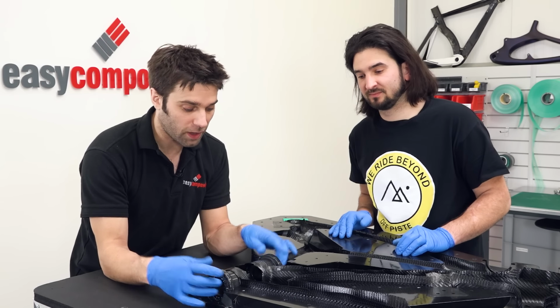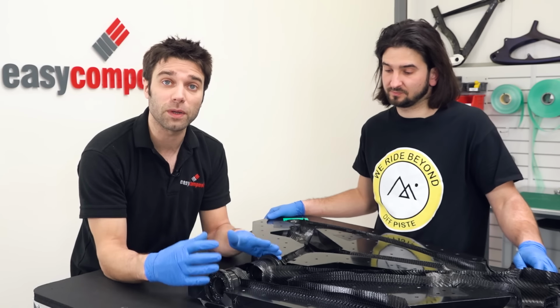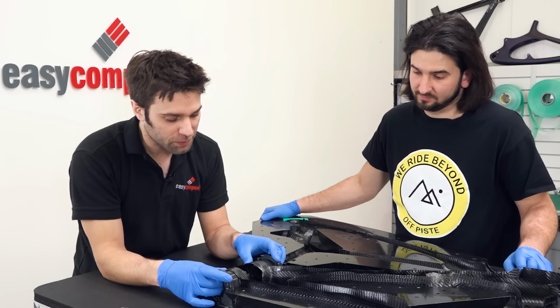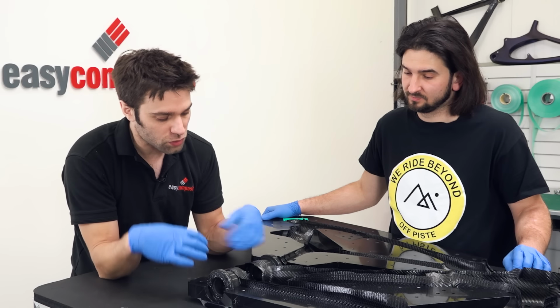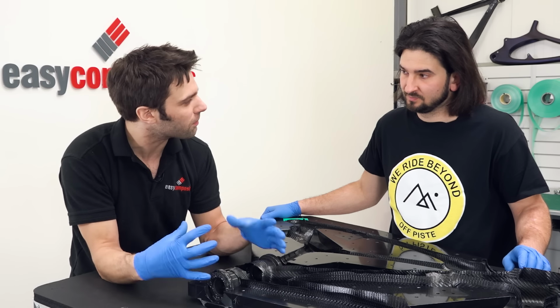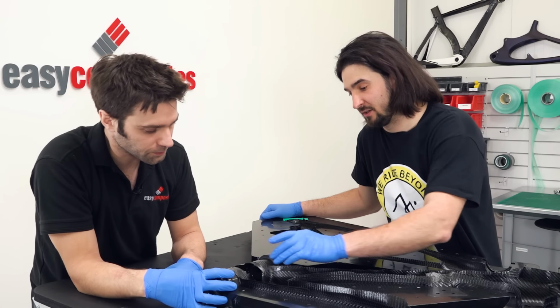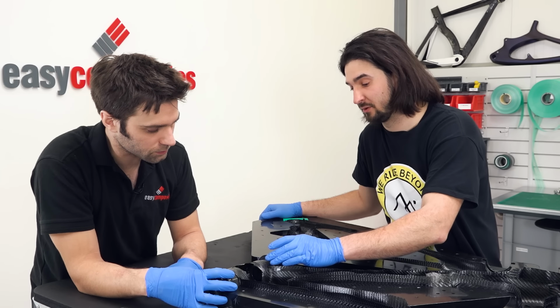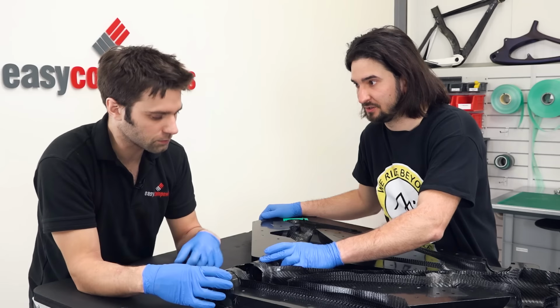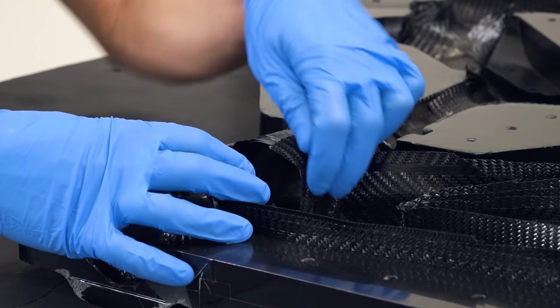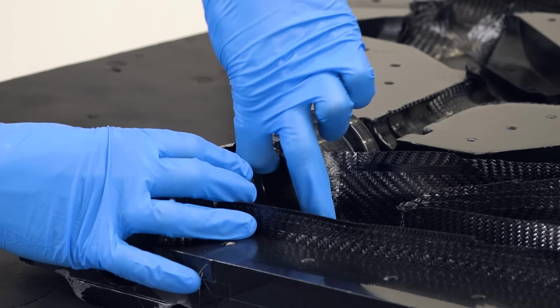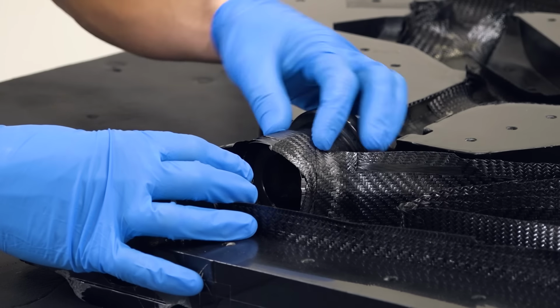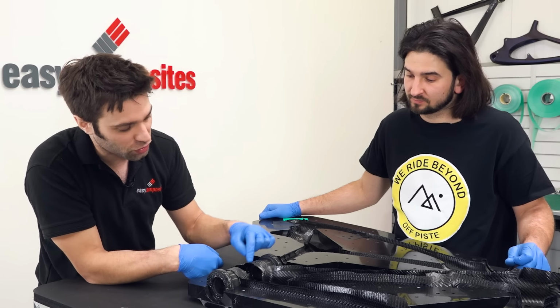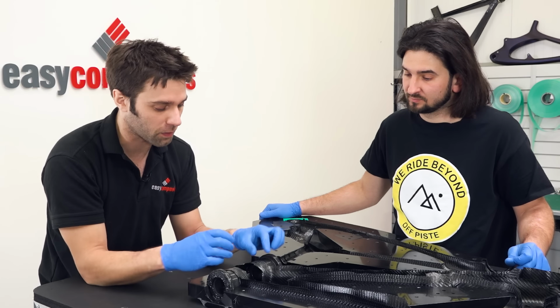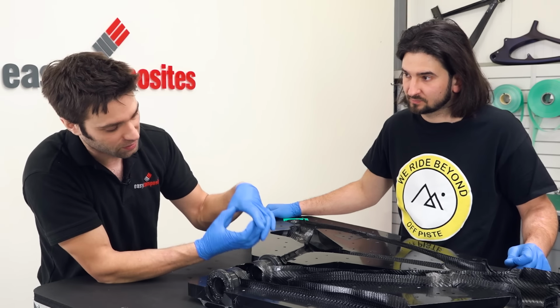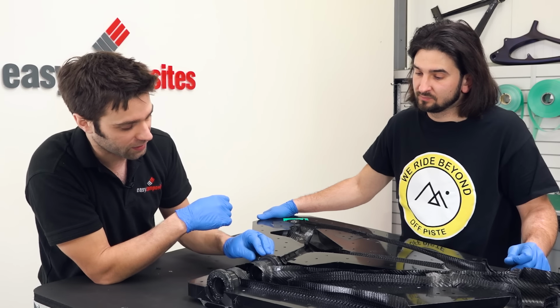So looking at the head tube, I can see we've got inserts in a very similar way to what we had around the shock mount here. But it does look a little bit more complicated. So could you run through what the layup is around here and what the main considerations are? So basically, again under the twill we have loads of UD wrapped around the bearing cups. Okay, so unidirectional, spiraled around there, because effectively that's where your steerer tube goes through, your bearings are sat into the frame there, and this is under a huge amount of strain coming up through from the forks. So that hoop strength that you get from the UD is absolutely key in that area.